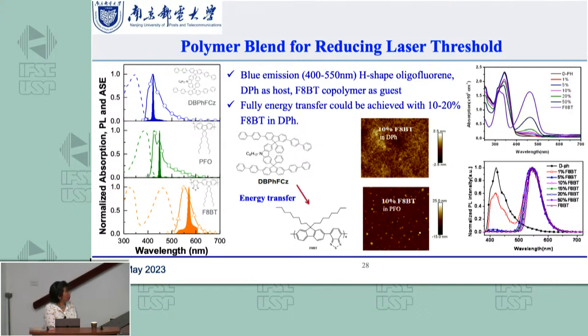But we also tried the PFO, and it doesn't work. The reason is, if you look at the morphology, this blend, the morphology is reasonably good. But with this one, you can see the phase separation. The small dots are the doping of the F8BT. It actually doesn't mix together, so we call that phase separation. That means energy transfer cannot happen.